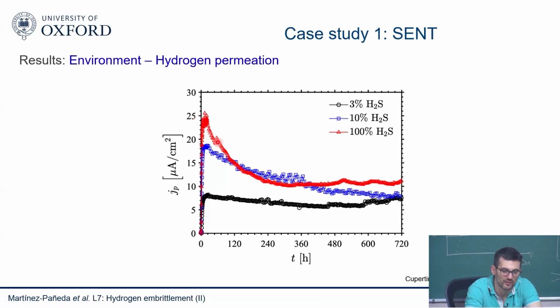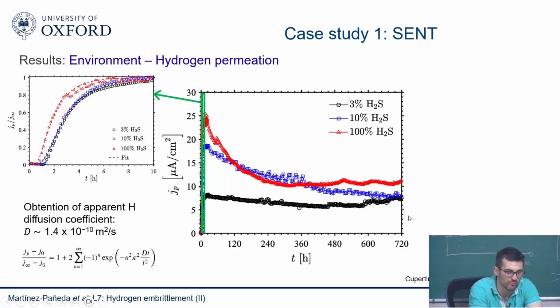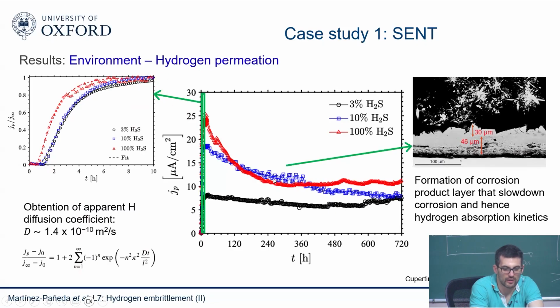You generate an oxide, and you can see the amount of hydrogen you have is coming down. So something is happening there. If you zoom in, you see the behavior that you would expect in a permeation test. So hydrogen is coming in, and this allows you to measure a diffusion coefficient. But then at some point something happens, and the hydrogen starts going down. And basically you see it experimentally. You form a corrosion product layer, so you have some sort of oxide that slows corrosion, and then the absorption kinetics. So there's something forming at the surface that is basically preventing hydrogen from coming in.